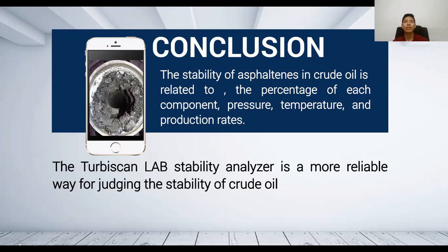Also, it was determined that the results obtained from the colloidal instability index can only be used as a spot determination of stability of the oil rather than a deterministic value. So we conclude that the Turbiscan lab stability analyzer is a more reliable way for judging the stability of the crude oil, and this method reduces the level of mistakes present in the classical colloidal instability index determination method.